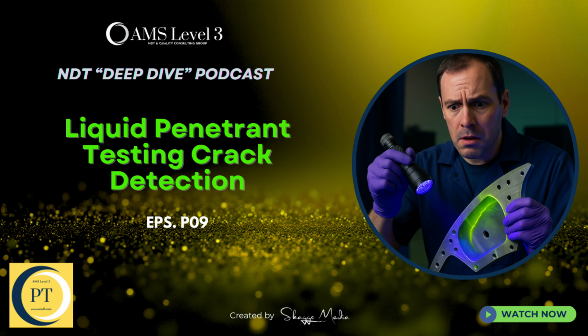It is. So, for example, checking common aluminum or magnesium alloys might need, say, 15 to 30 minutes. But if you're inspecting critical stainless steel welds or forgings, that time jumps significantly. You might be looking at 30 to 60 minutes easily. So the part itself really dictates the process, doesn't it? Not just what the technician feels like doing.